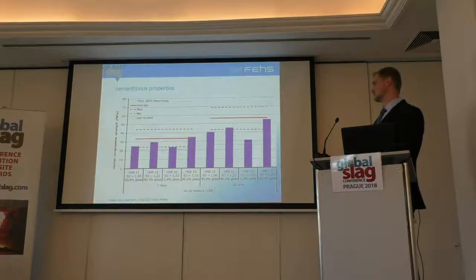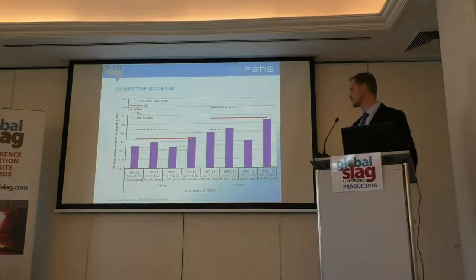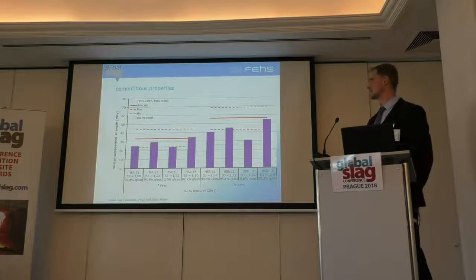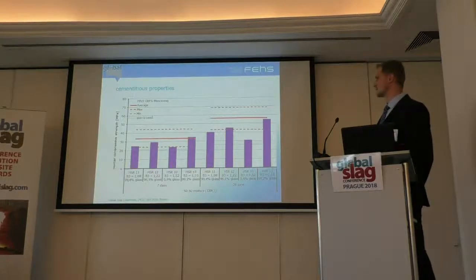granulated blast furnace slag, and by increasing the basicity we should get very good compressive strength, but due to the very low glass content there was no real impact on the compressive strength, so that we are here in the area of quartz sand. The last one, where we also added the alumina, was then in the range of the average of our monitoring.